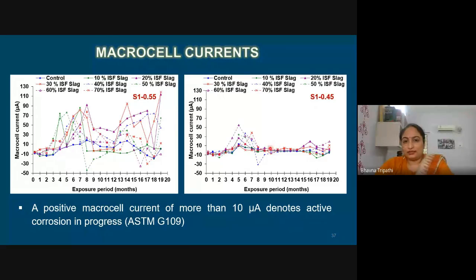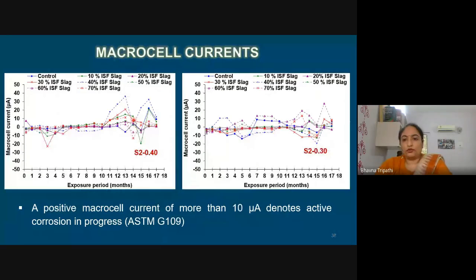Largely, what we see is the change in current, and how do we indicate that corrosion is going on? We take a positive macro cell current of more than 10 microampere to be indicative of active corrosion in progress. So wherever we witness a macro cell current of more than 10, this indicates that yes, corrosion is going on. Otherwise, under this concrete mix, it is very difficult to see a high rise in macro cell current, and most of the time the current is less than 10 microamperes. For the other mixes, there is no need to explain the macro cell current. These are the currents.